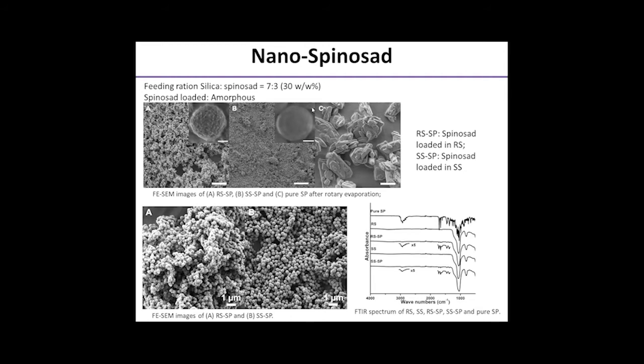in this presentation. The field emission scanning electron microscope images show that both nanospinosad maintain the spherical morphology and the rough and smooth surface topology after the spinosad loading. Without using nanocarriers, the pure spinosad after rotary evaporation formed micron-sized crystals. Such crystals cannot be observed in the high magnification and the lower magnification SEM images of the two nanospinosad, indicating the successful loading of spinosad within silica nanoparticles.